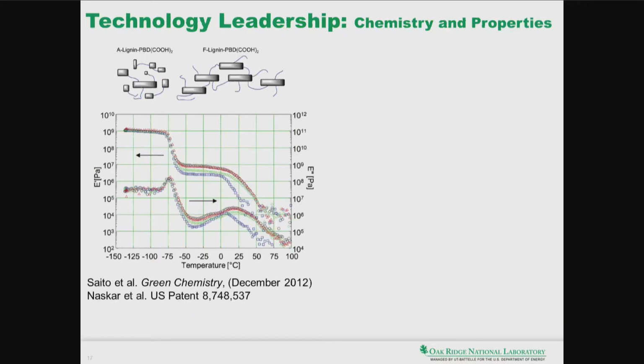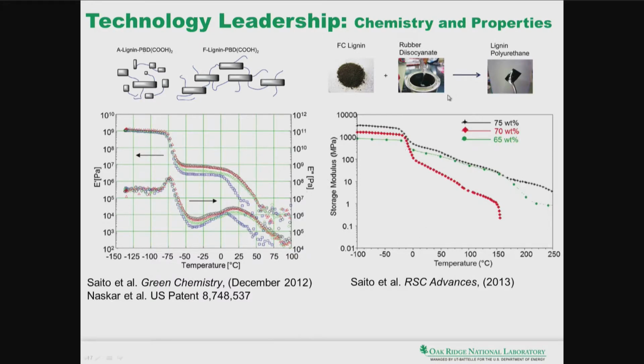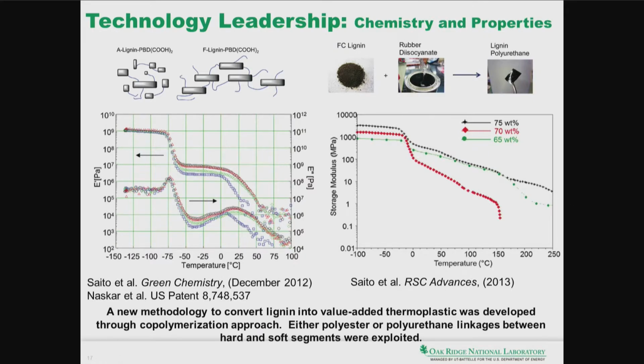We published that, and then we also explored polyurethane chemistry by utilizing rubber diisocyanate. Lignin can be coupled with diisocyanates to form polyurethane. It's a very straightforward chemistry. In absence of moisture, it can give great yield, unlike polyester. And you can see the dynamic mechanical property got significantly improved. In the previous case, the modulus was dropping near room temperature. Here now it is flowing near 150 degrees Celsius. In some cases, it doesn't even demonstrate that flow characteristic. So we made significant improvement by doing the chemistry before we started this particular project.